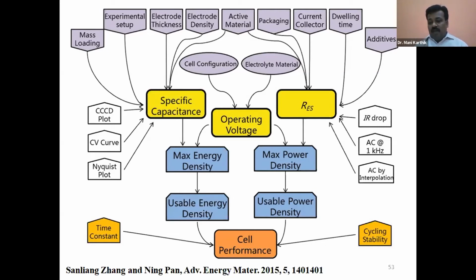And if your electrodes are very thickly coated, then you have ionic resistance, ion diffusion resistance inside the electrode. That will also affect. So these all arise when you are making the cells, because you have the carbon coated. That's why we are using carbon coated aluminum, in order to avoid the resistance between the electrode and current collector. So in order to avoid that, carbon coated aluminum will help. You can adjust very nicely with our material on the carbon coated aluminum foil, then we can get very nice results. This is very important. You need to control all the parameters, then only we can increase the specific capacitance.